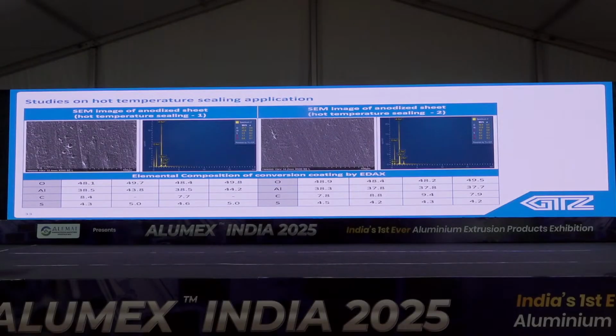Now the hot sealing. It is also similar to medium temperature as far as the pictures are concerned. The first picture is the half sealing stage, and the second is the full sealing stage. Here there is no metal, so you can see from the carbon, which is the representative organic content, that in half sealing carbon is not uniform and the average is still less, and for full sealing carbon is everywhere, and the content is also higher than the half sealing.